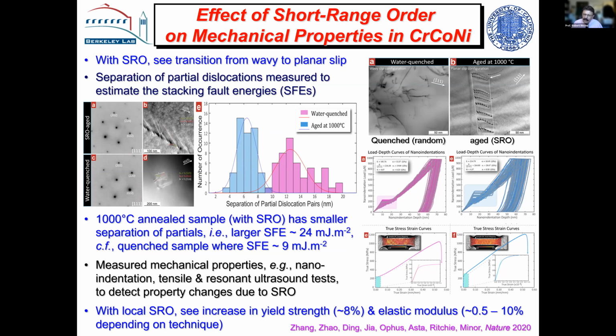And we haven't got this totally sorted out yet, but we firmly believe now that when you get short range order, dislocations moving on these slip bands will tend to effectively annihilate that order. And we think that process promotes twinning. So we think short range order, and we're still trying to prove this, is implicit in this sequence of deformation mechanisms, which is so important to the strain hardening, which gives this material its incredible toughness. It may not affect the macroscale properties because we don't really know whether we can totally inhibit order when we water quench and generate it when we age. We don't understand the kinetics of this process yet, and that's the difficult part.